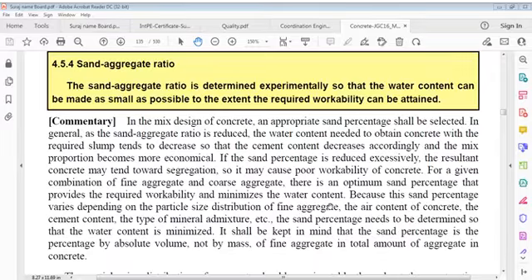so it may cause poor workability of concrete. For a given combination of fine aggregate and coarse aggregate, there exists an optimum sand percentage that provides the required workability and minimizes water content. Because this sand percentage varies depending on the particle size distribution of fine aggregate, air content of concrete, cement content, and type of mineral admixture, the sand percentage needs to be determined so that water content is minimized.